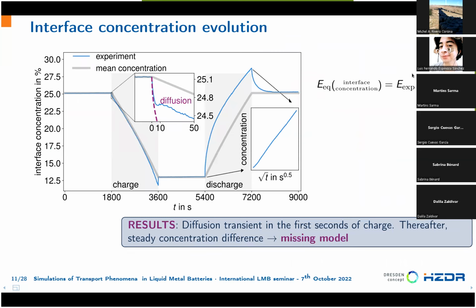Now we invert the previous equation and compute the interface concentration here in the form of a molar fraction. At the beginning, we have a uniform concentration, and then we have this charge phase. If you look at the charge phase, we see that there is also a really short diffusion phase, only 10 seconds over 30 minutes of experiment, in which the concentration evolves like diffusion. And then the concentration difference is set to a fixed value. So we have a very small concentration difference present during the charge phase.